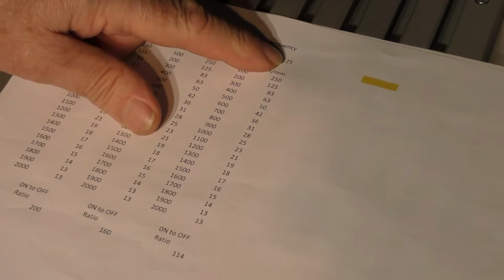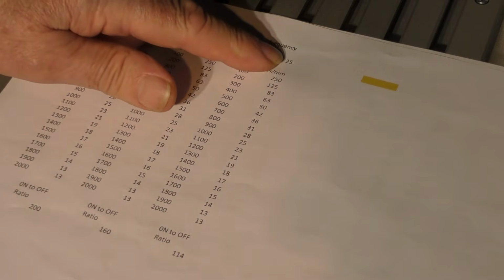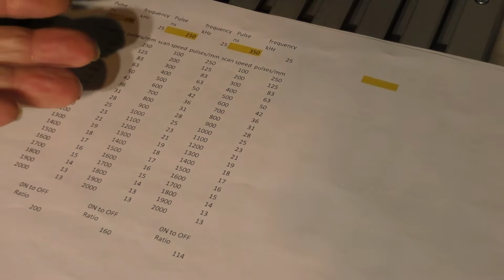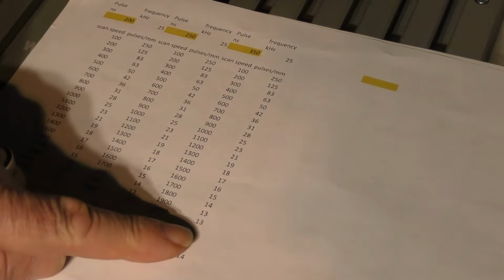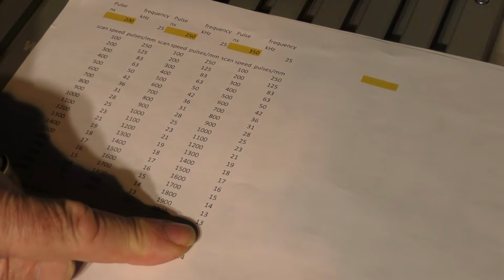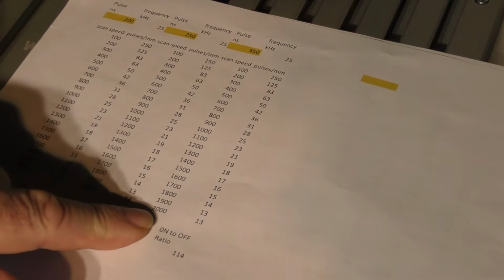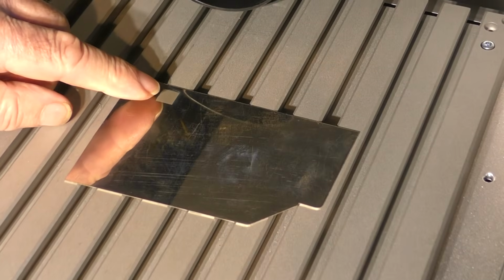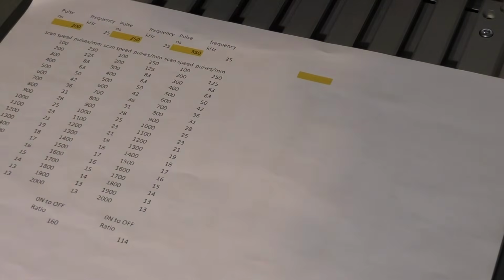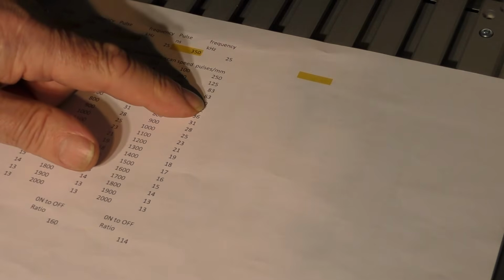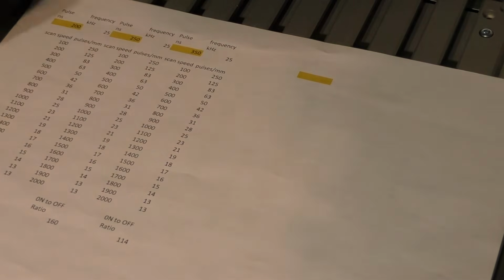We're only running at 25 kilohertz, remember. So therefore the repetition rate is very, very slow. So we're only getting 13 pulses per millimetre at 2000. But look, we did this amount of damage with just 13 pulses per millimetre. If I reduce it to 500, I'm now going to put 50 pulses per millimetre in. So I don't think it takes a genius to realise that we're going to put a lot more power into the surface and we're going to do a lot more damage.